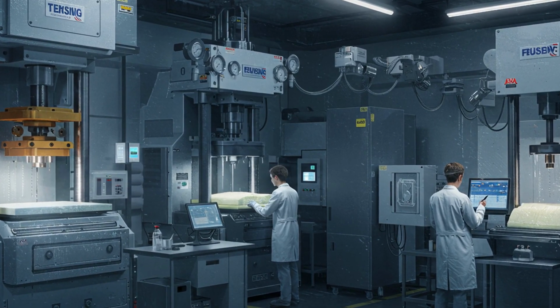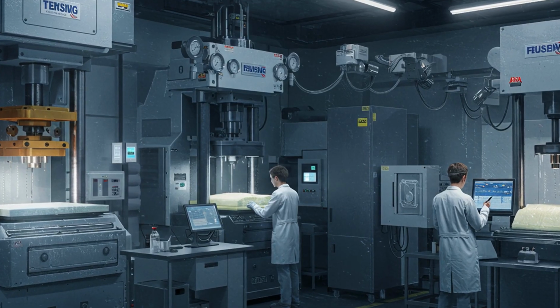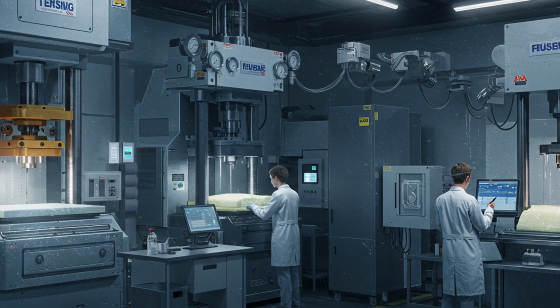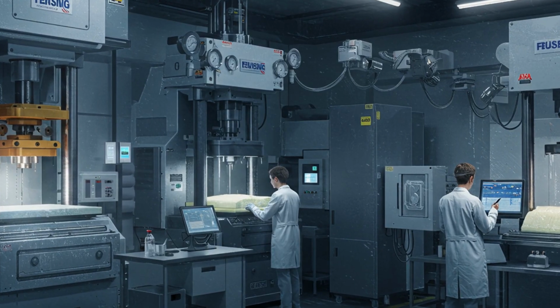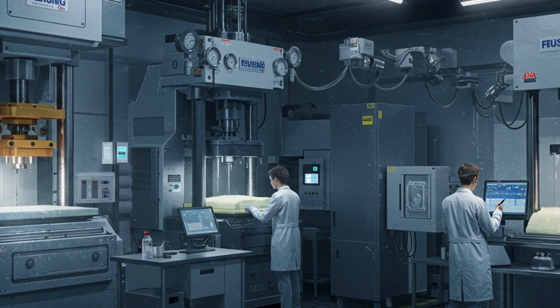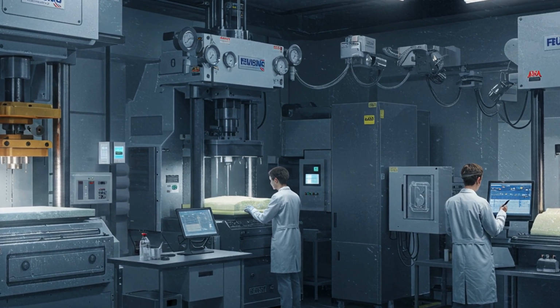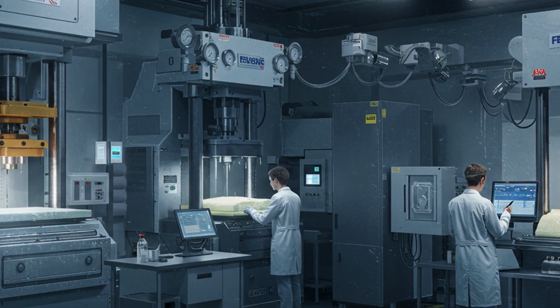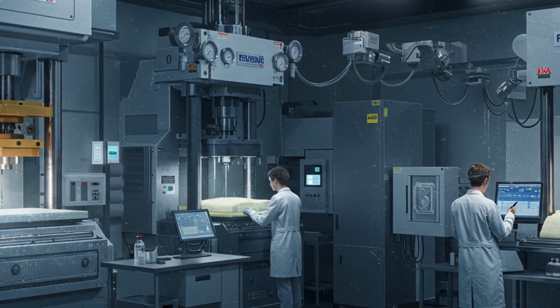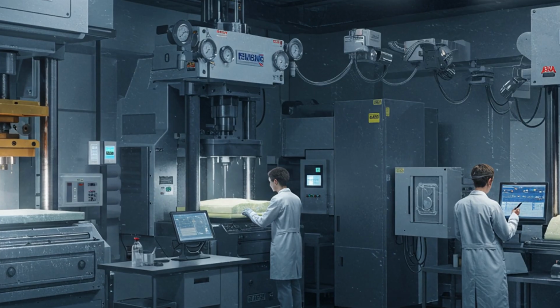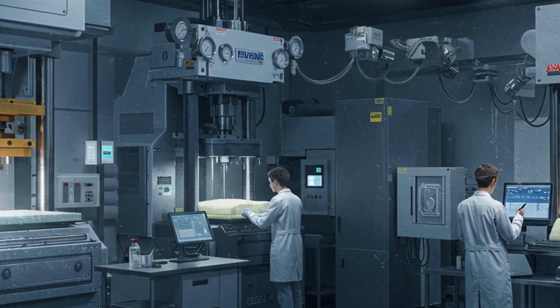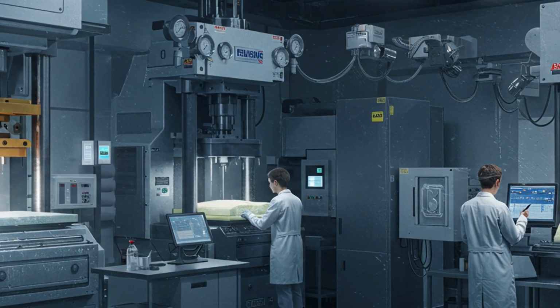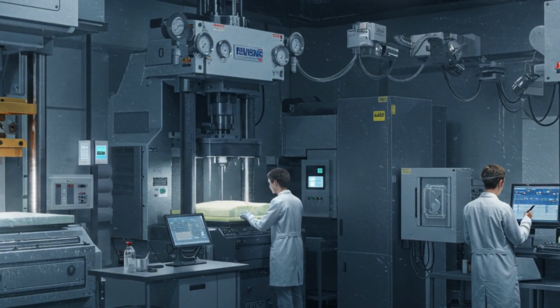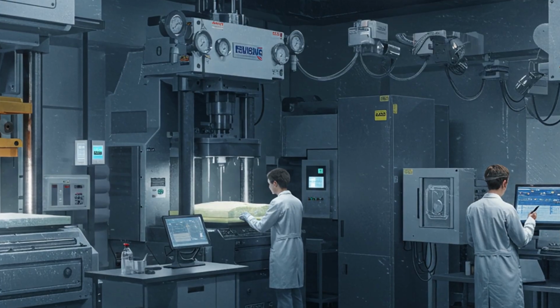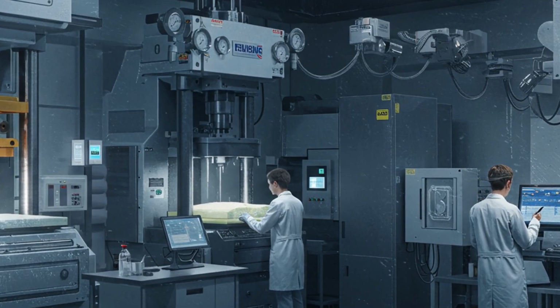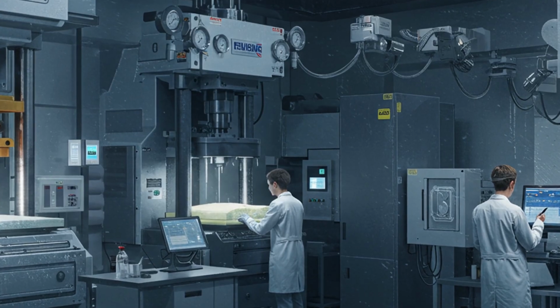Thermal aging chambers expose samples to elevated temperatures to predict long-term behavior. Flammability tests follow regional standards. For the U.S., manufacturers reference California TB 117-2013 performance pathways and use barrier materials or compliant additives. Off-gassing is measured in controlled chambers to quantify VOC emissions over time. Any batch that fails tolerance for density, IFD, or recovery is recycled or reprocessed, cut into carpet underlay or automotive insulation. This chapter visits the labs where instruments, jigs, and relentless protocols separate reliable products from rejects. The goal? Guarantee comfort, safety, and years of predictable performance.